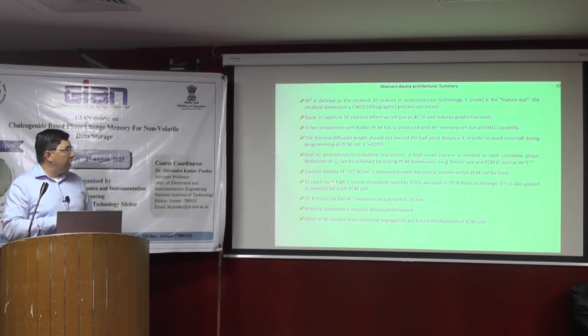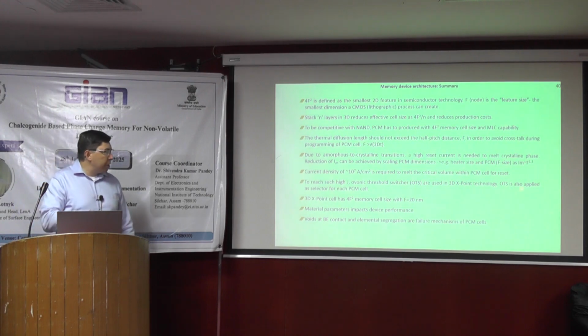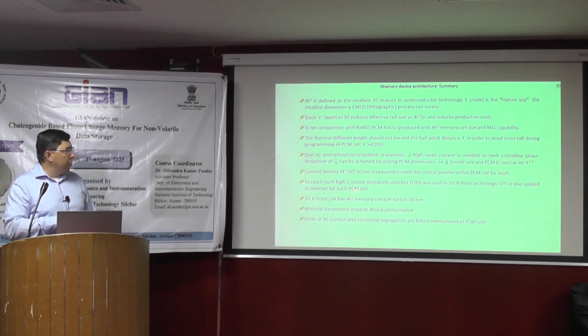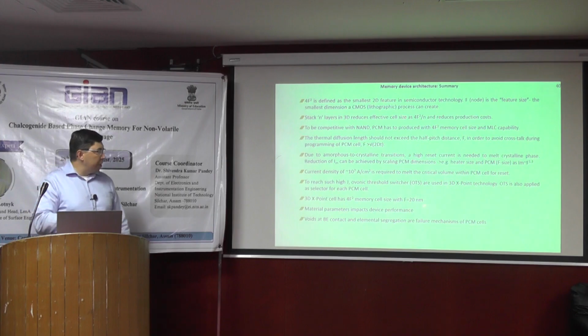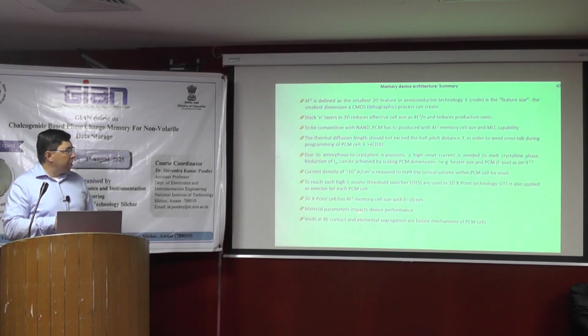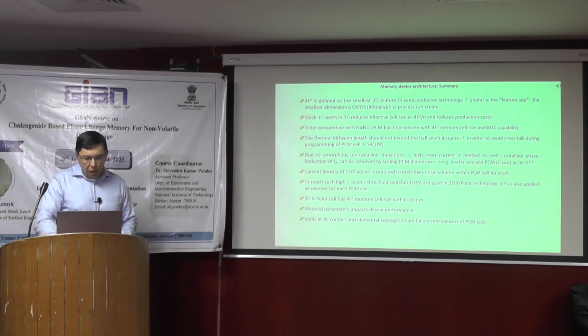And to reach such high current density, Ovonic threshold switches are used in 3D XPoint technology. OTS is also applied as a selector for each PCM cell. The 3D XPoint cell has a 4F2 memory cell size with a node size of 20 nanometers. And material parameters also impact device performance. We will consider this in the next lectures. And voids at the bottom electrode contacts and elemental segregation are failure mechanisms of PCM cells.